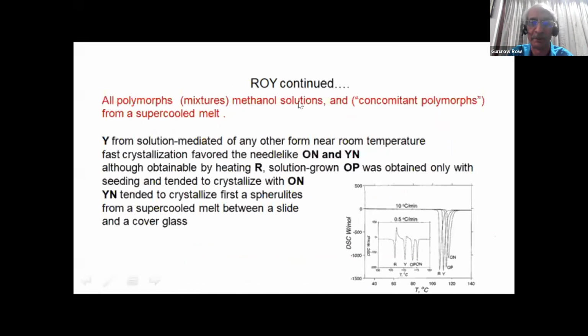from methanol solutions. Here is the DSC of the 5 different polymorphs. You see that they're all within a very small melting zone. So one can convert to the other very, very rapidly. Indeed, when the crystallization is affected, the polymorphs come as mixtures, and therefore one has to separate them. The separation is done by repeated crystallization experiments, as we will detail below.